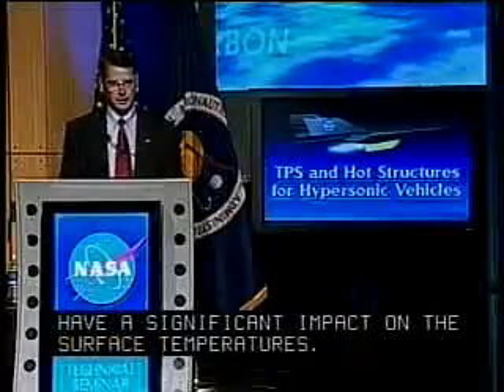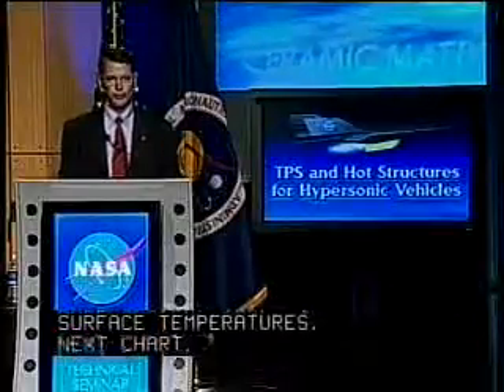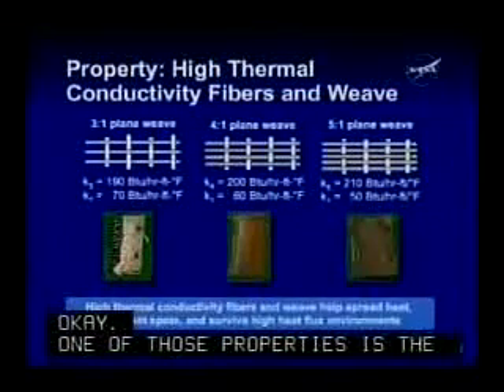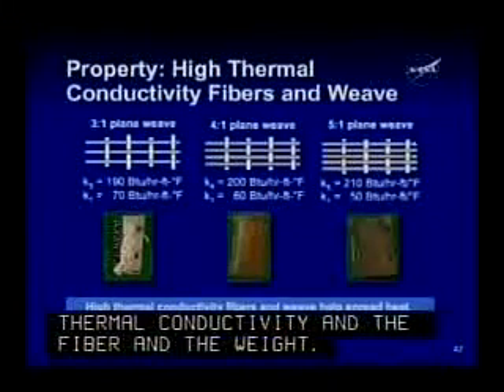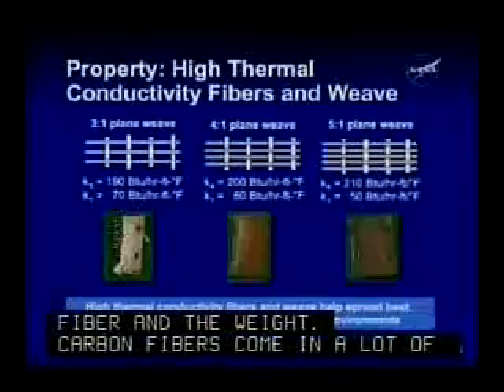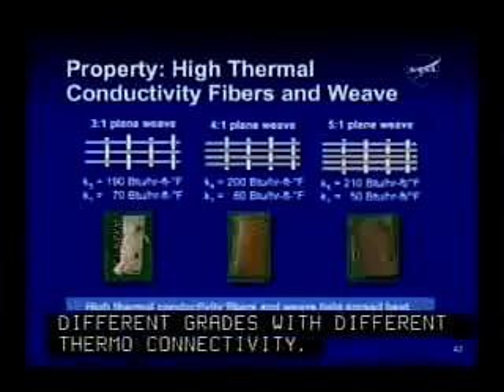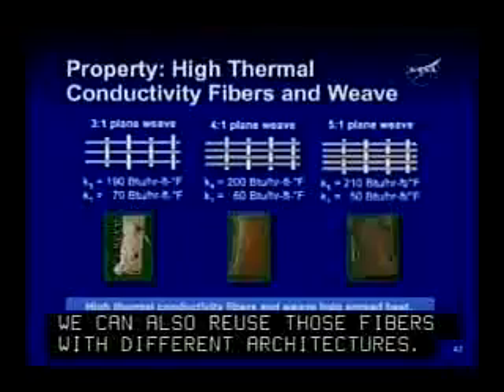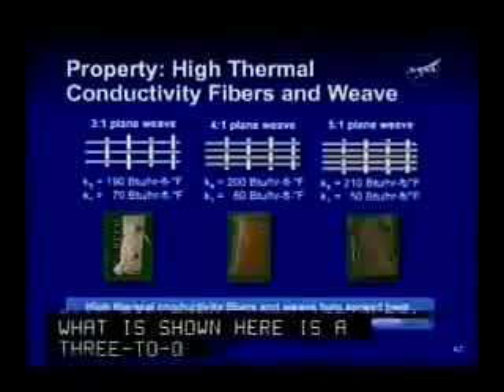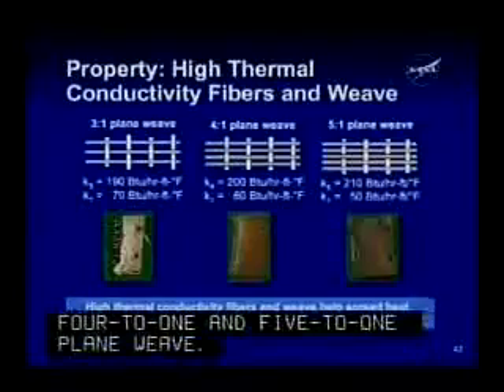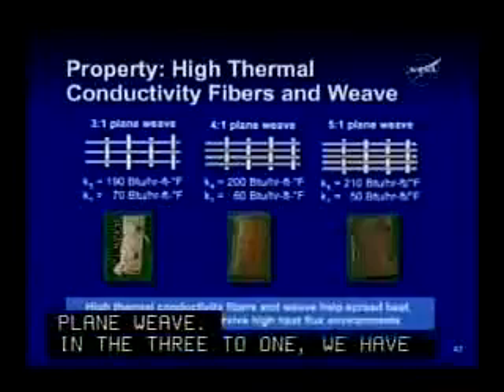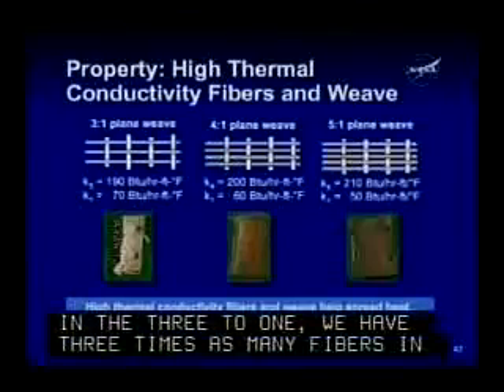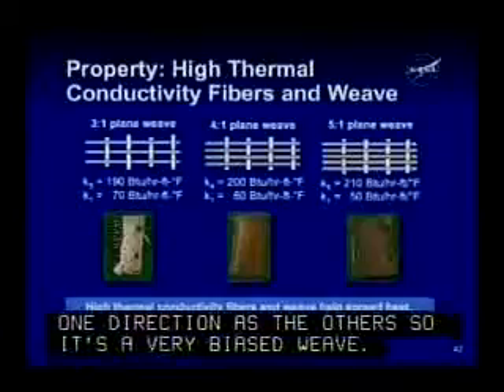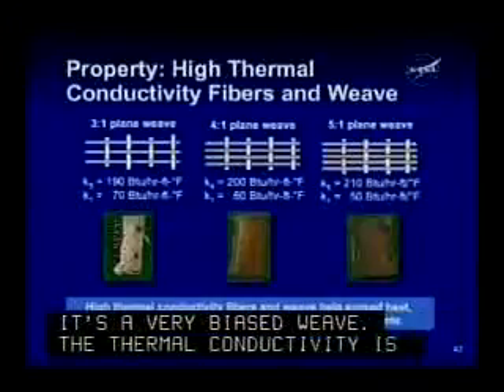Next chart. Okay, one of those properties is the thermal conductivity of the fiber and the weave. Carbon fibers come in a lot of different grades with different thermal conductivity. We can also weave those fibers with different architectures. Shown here is a 3-to-1 plane weave, 4-to-1, 5-to-1 plane weave. In the 3-to-1 plane weave, we have 3 times as many fibers in one direction as the other, so it's a very biased weave. The thermal conductivity is shown here.